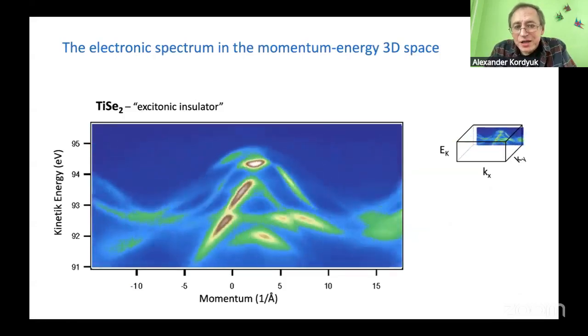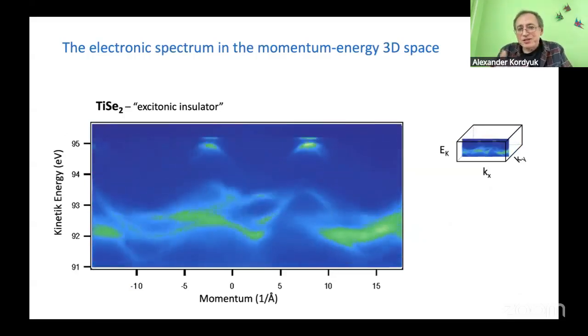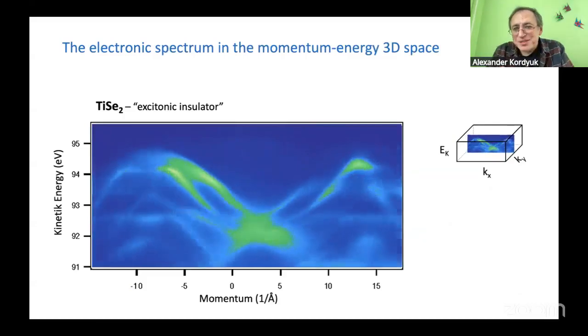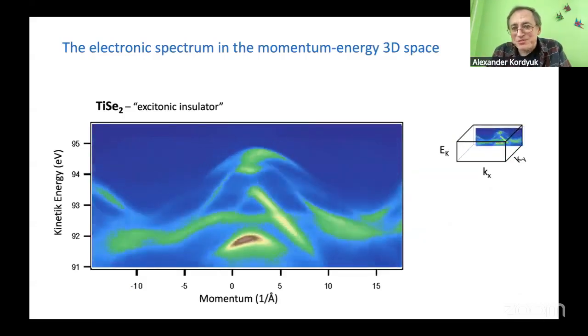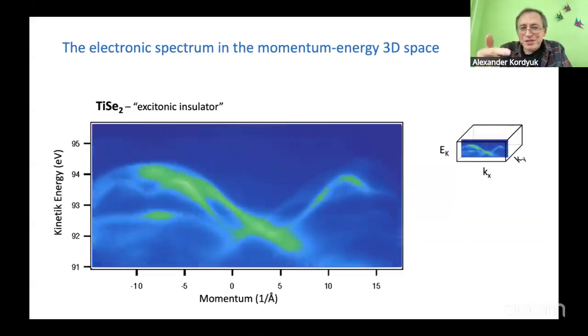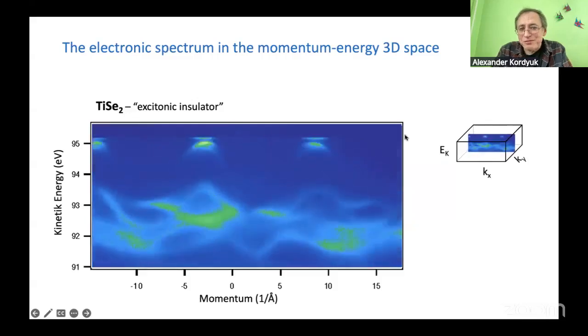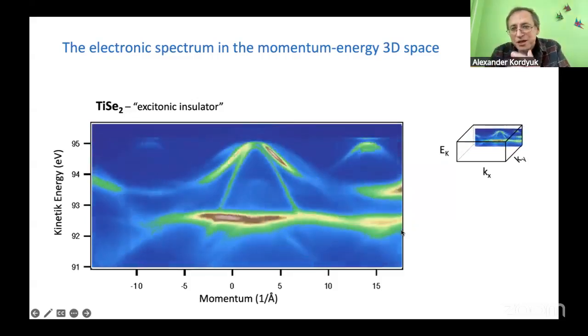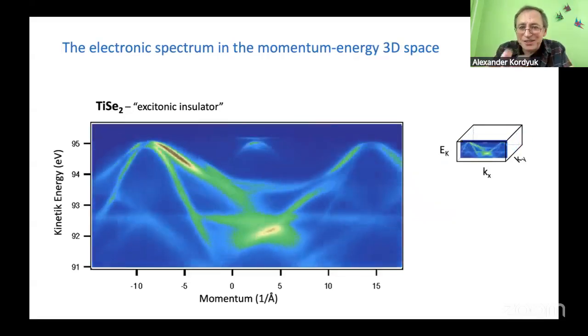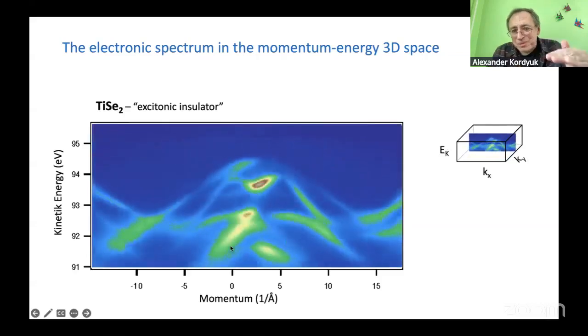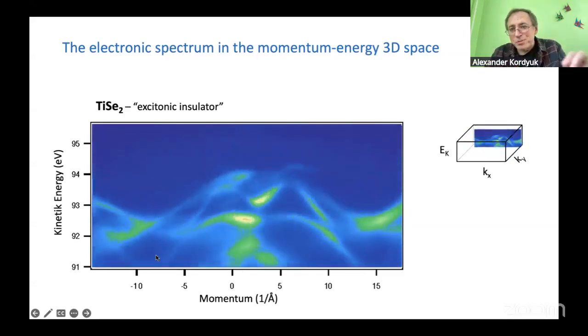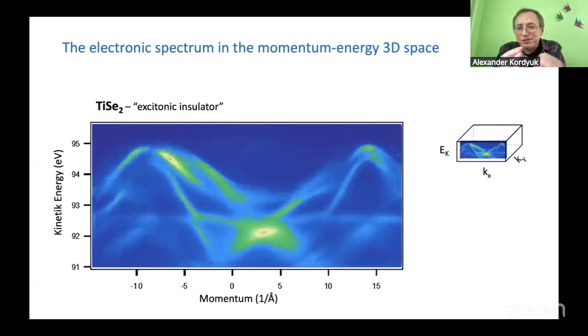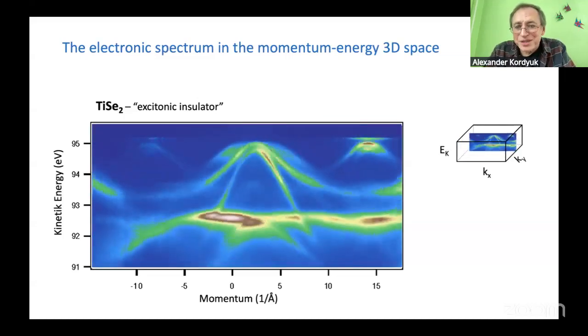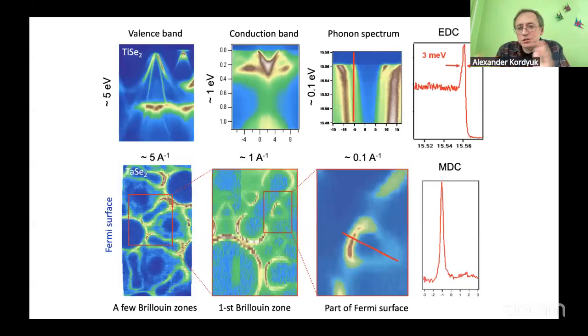Therefore, this shows the real distribution of the electrons. This is experimental data, and you see there are many bands. Why is it moving? Because it is just a plane representation. This movie represents three-dimensional space where you have kx and ky, and vertically you have energy. Here is the Fermi level, and this is the distribution of the electrons. From this distribution, you can understand the interaction of electrons with the crystal lattice in terms of band gap, band width, and harmonics. And with this smearing out, you can get information about important interactions. We also need to compare it with calculation to understand which band is where. And we need quite a long range of parameters.